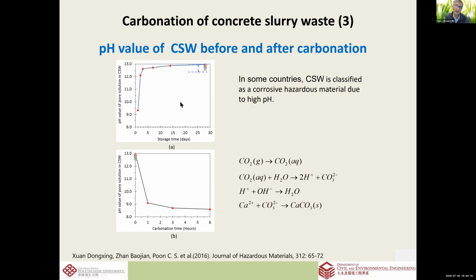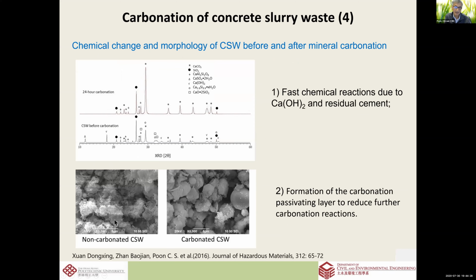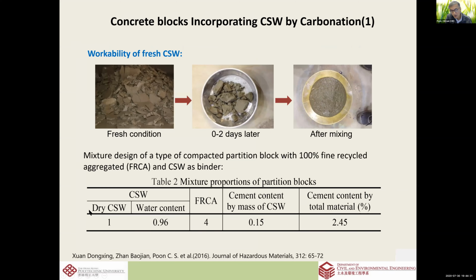This shows the change of pH value after carbonation, and the change of the microstructures. But what we try to do is to make it a truly eco-friendly material with the fresh waste. This waste is cement with a lot of water and also some very fine sand. After 2 to 3 days, it's still workable. Although it's a lump, after 2 days when we mix it, because of the very high water content, it's still workable.